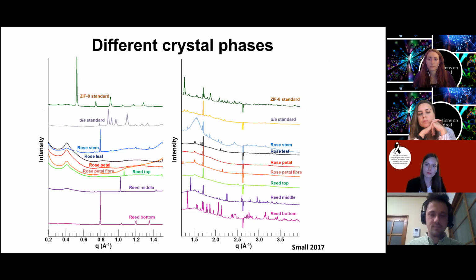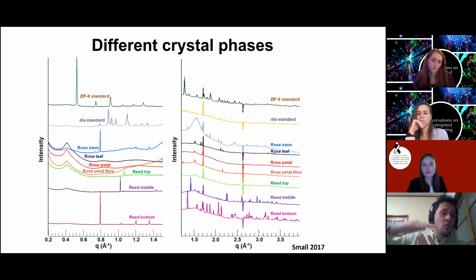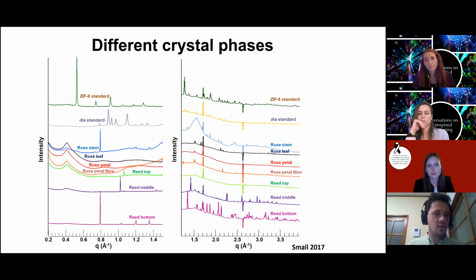So that's interesting also. This is just a big data dump from the synchrotron to show you that we did do more hardcore science. Since this is very conversational, I want to give it some scientific legitimacy. But we used the Australian Synchrotron to look at the scattering profiles of different plants, roses, reeds. We also did some grass as you go up the plant. So starting from the very top to the very bottom, taking different time points. And we actually saw different crystal isoforms appear at different lengths and different distances and different times.